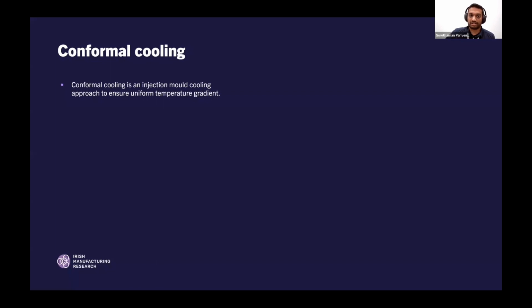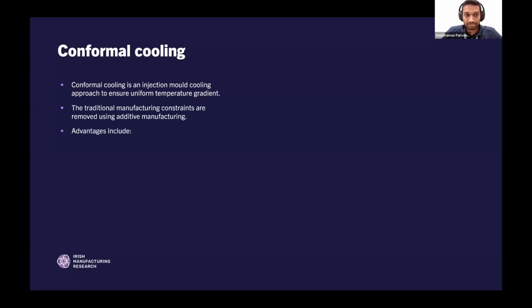So how can we address this? We can do that by conforming the cooling channels as close to the part shape as we can. But traditional manufacturing methods are constrained in this regard because the path lines of these cooling channels are 2D in nature. These 3D conformal cooling channels can be manufactured by additive manufacturing, because that's a layer-by-layer manufacturing technique, and we can easily achieve these 3D cooling channels. Some of the advantages of conformal cooling include, as I said, lower cycle time, and due to the uniform temperature gradient, we can minimize part distortion and defects, and there's also a reduction in energy.